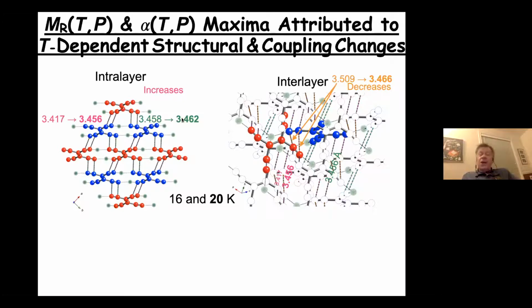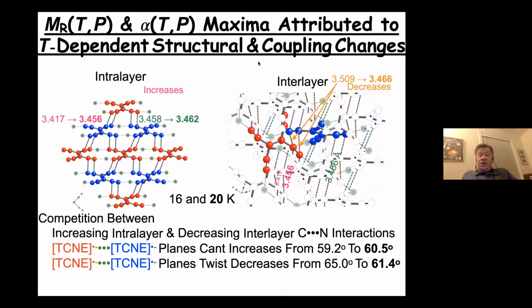Now the interlayer between the two different layers actually have a slight decrease from that. And furthermore, there's a change in a cant between the angle, the planes, as I mentioned earlier, between this red plane and blue plane. It goes a little bit higher than 59.2 degrees. And also, which I don't show you, there's actually a twist in these planes going from 65, dropping down to 61.4. So not big changes, but there's only a 4-degree temperature change. And so we believe these changes play into why there is an increase and then subsequent decrease in the canting angles as a function of temperature and or pressure.